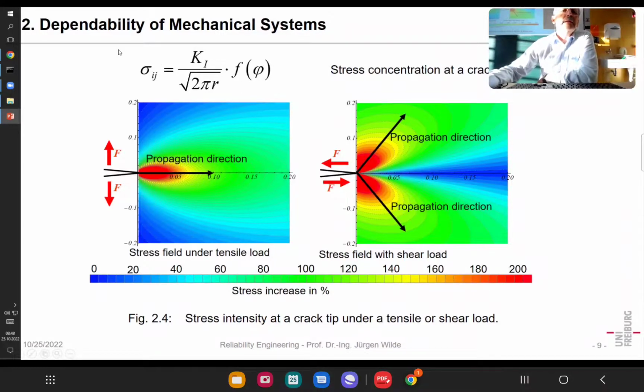Here, that angle, in fact, that's the angle under which, when you go from the tip, has an influence. In the most important case, which is just tensile, perpendicular to the direction of the crack, you have the maximum stresses. And here as it's shear, it goes more to something like 45 degrees or around that. That's the angle between the crack direction and the direction in which you look here.